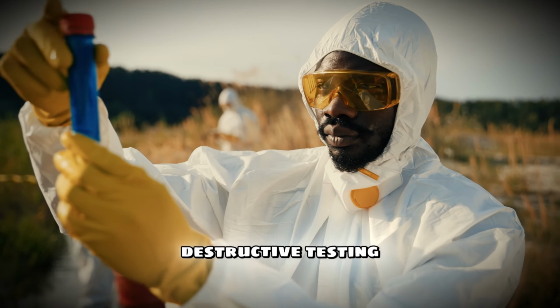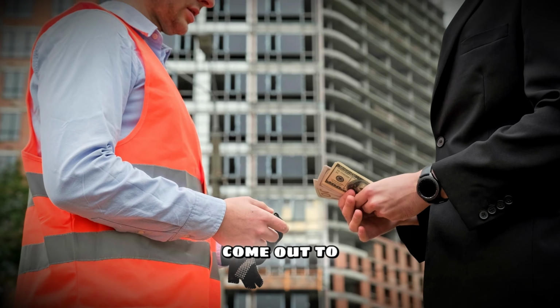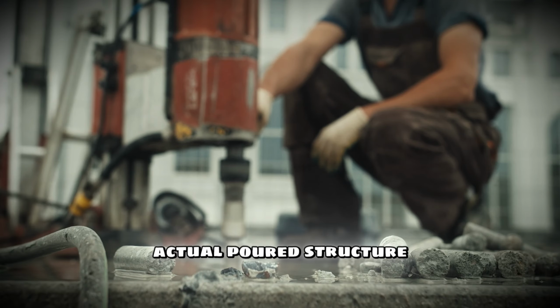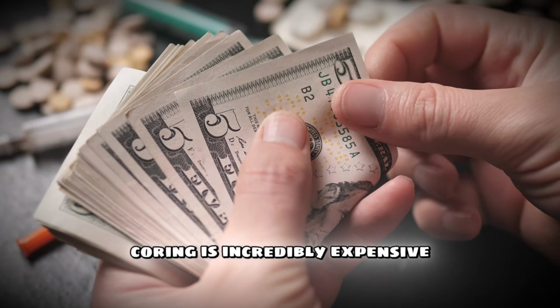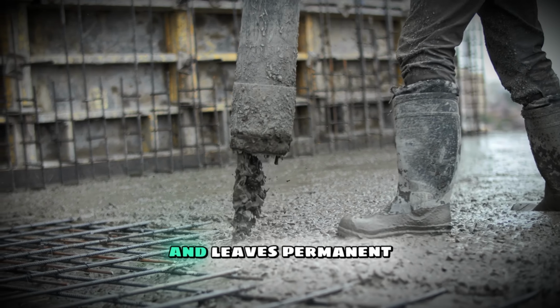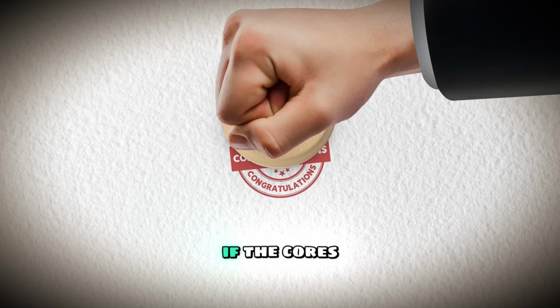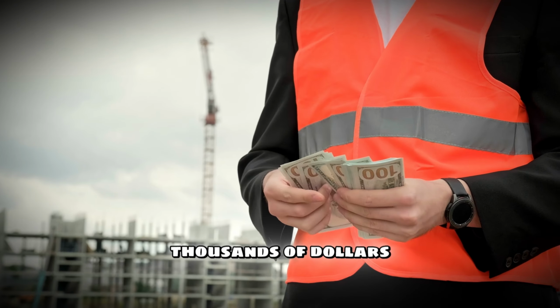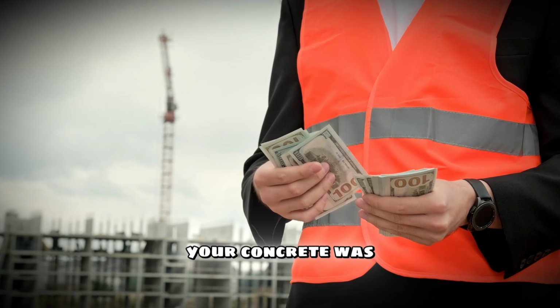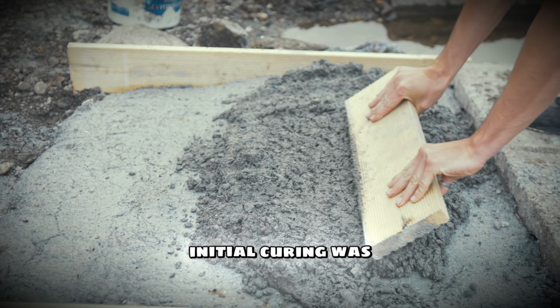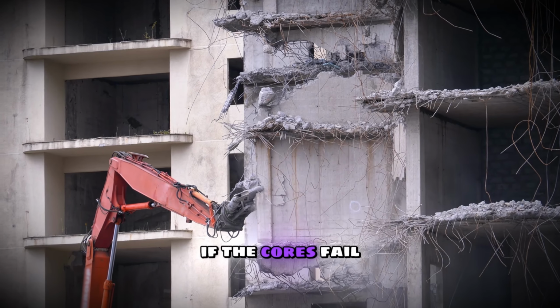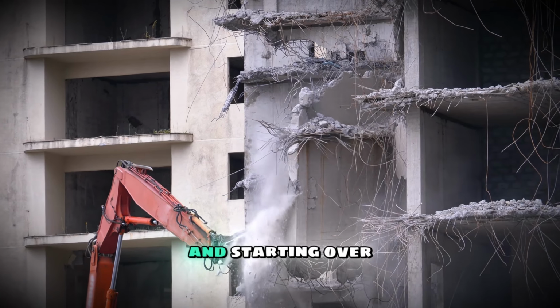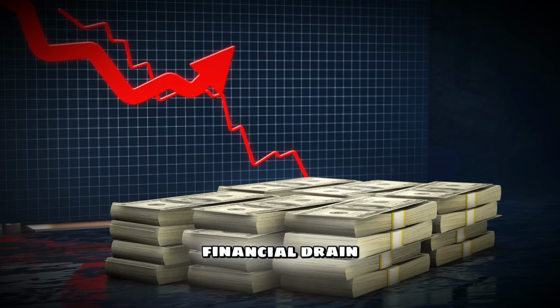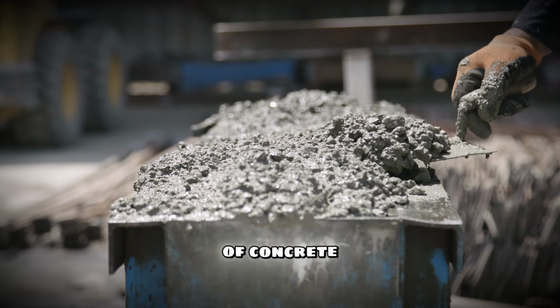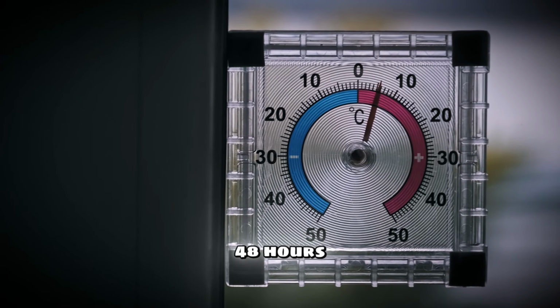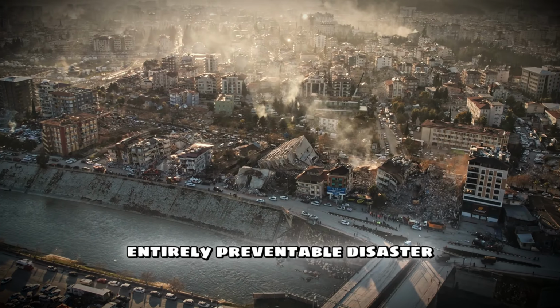Next comes the destructive testing. You now have to pay an independent firm to come out to the site, drill core samples out of the actual poured structure, and test those. Coring is incredibly expensive, time-consuming, and leaves permanent patches in your finished product. If the cores pass, congratulations. You just spent thousands of dollars and lost a week of work to prove that your concrete was fine all along, and that your initial curing was just terrible. If the cores fail, you might be looking at tearing out the concrete and starting over. All of this chaos, all of this financial drain, simply because a plastic mold full of concrete wasn't kept at the right temperature for the first 48 hours. It is an entirely preventable disaster.